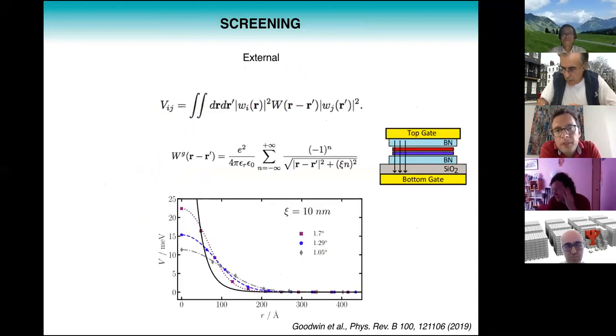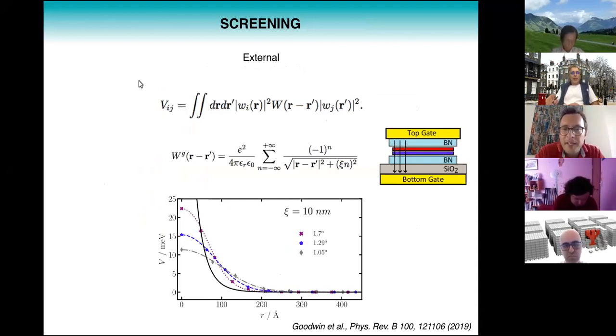Okay, so next, of course, I want to talk about another effect of long-range interaction, and that is screening. This is particularly interesting because screening is fundamentally different in a two-dimensional material than in a three-dimensional material. There are new control knobs in a two-dimensional material that we simply don't have in 3 dimensions. So there are things that you can do to twisted bilayer graphene that you couldn't do to the cuprates. One thing that you can very easily do is what we call device engineering. This means you can change the interactions between electrons in the twisted bilayer graphene by changing the environment in which the twisted bilayer sits.